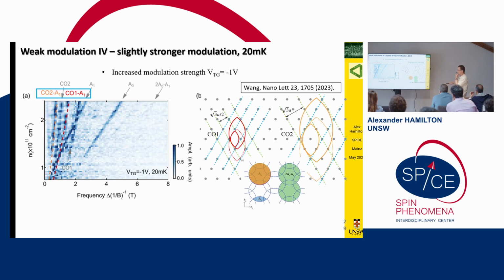When I go from reciprocal space back to real space, you rotate by 90 degrees. This is the real space electron trajectory, and this is the crystal lattice that I've imposed. And whenever that real space electron trajectory fits nicely inside the artificial lattice, I get a minimum in the resistance, and therefore I get these additional frequencies. This can only happen for the honeycomb lattice because I've got this symmetry of the direction of the lattice and this direction of the lattice.